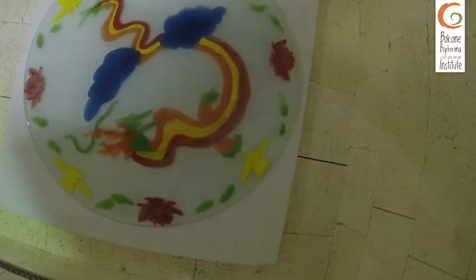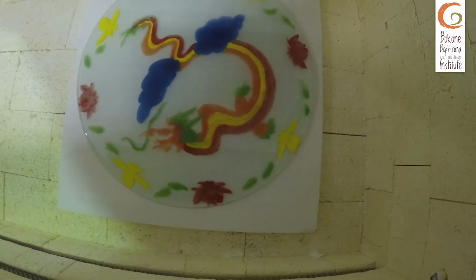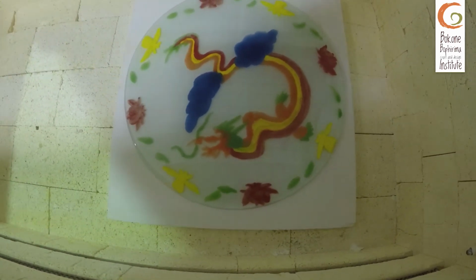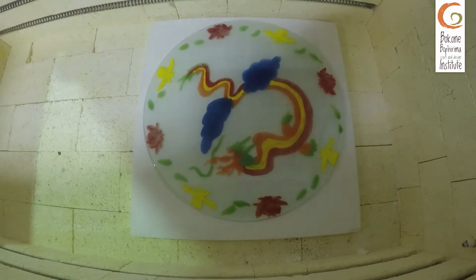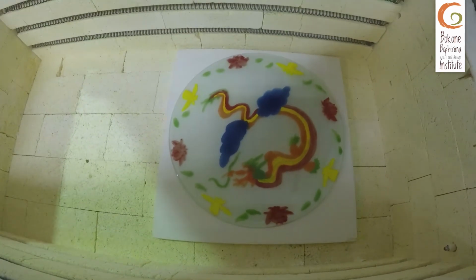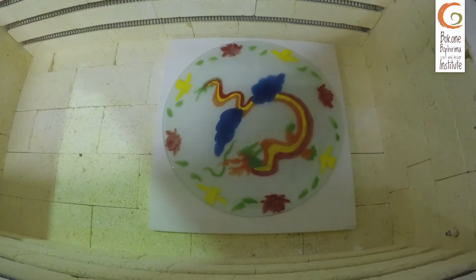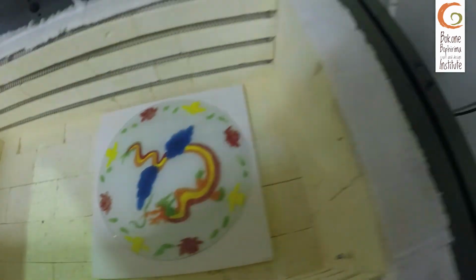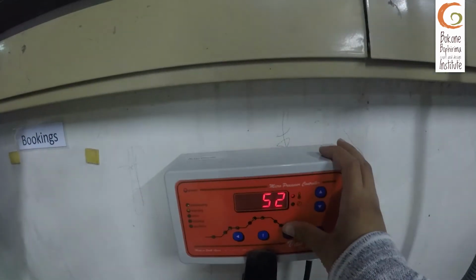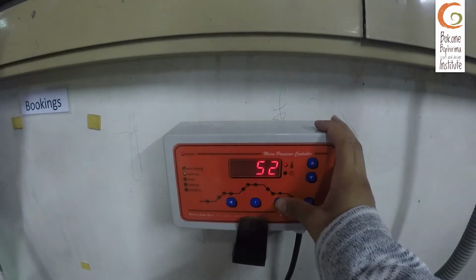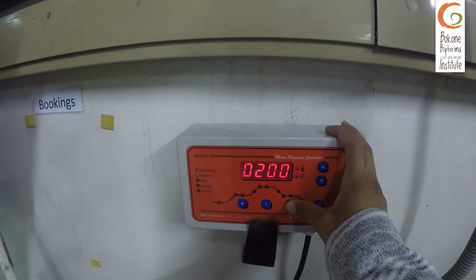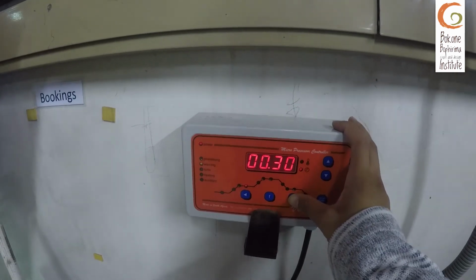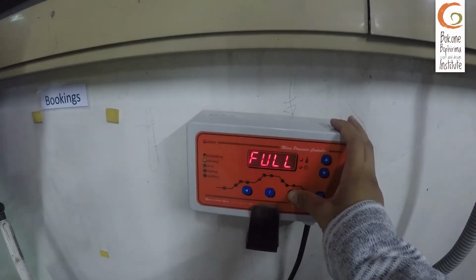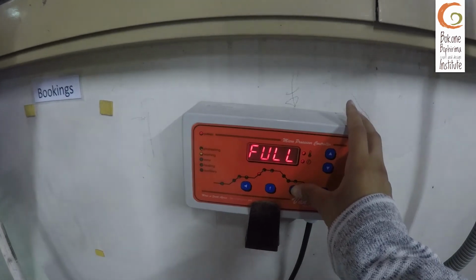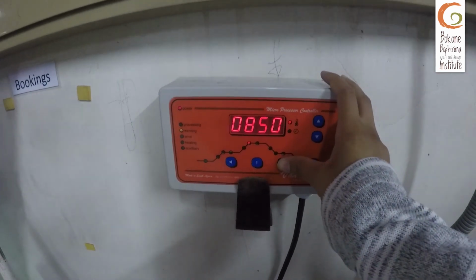The bottom layer, which is our color foundation, has been fired to 850 degrees, and it has been placed on a prepared kiln shelf which was coated with plaster of Paris applied with a brush. At our kiln program, the temperature is reading 52 degrees. We are starting immediately, so there's no need to start a timer, and we're going up the ramp at 200 degrees to 680 degrees, and we let it soak for 30 minutes.